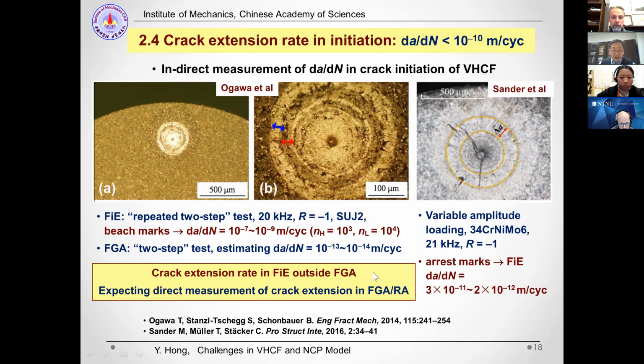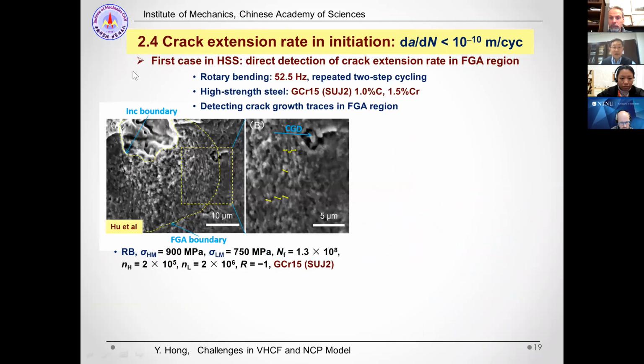So such efforts are devoted to the crack extension rate in the fisheye region outside the FGA. We are expecting direct measurements of crack extension in the initiation region of the FGA. This is the first case of crack extension rates obtained in high strength steel, and we use a kind of repeated two-step cycling to catch the crack growth traces in the FGA region, and then we are able to obtain the crack extension rate in this region directly.